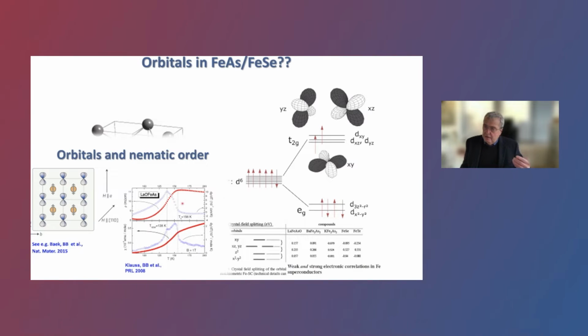And in these 1111 type systems, in contrast to other systems, this structural phase transition, or this nematic phase transition, if you would like to call it that, or this orbital order, if you want to call it that, is well separated from the magnetic one, which occurs 15 Kelvin lower in temperature. That's already seen in the very early work which we did on powder crystals. Okay, so that's the starting situation. We have these orbital degrees of freedom, we have these nearly localized states, very bad metallic states, and of course we have magnetism in the game in these systems.